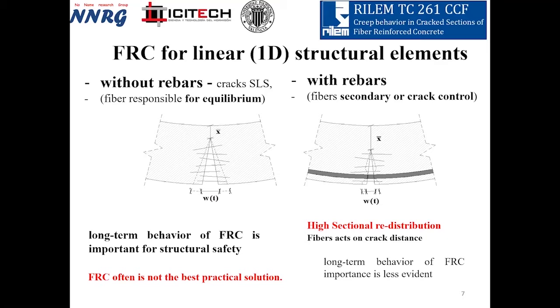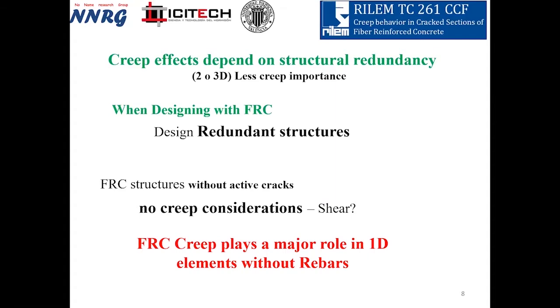In the right case, when you work with rebars, you can have a crack, and in this case, you have a big redistribution. If the fiber has a loss of capacity because of creep, this loss of capacity is always absorbed by the rebars. In this case, maybe the effect of creep is not so important. Then usually we work with that, but if you think of fibers, usually you think of a very structural redundancy. And then we work on 2D or 3D elements.